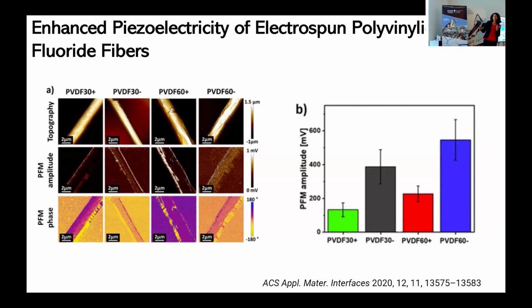So the numbers there represent the humidity, so that's 30%. The signs there represent whether we're applying a positive or a negative voltage. They look the same-ish in topography, but when you start looking at the PFM images, you can start to see some differences. That's summarized in this table here. This is looking at PFM amplitude for these different fibers that were produced under different conditions, and you can straight away see a winner.